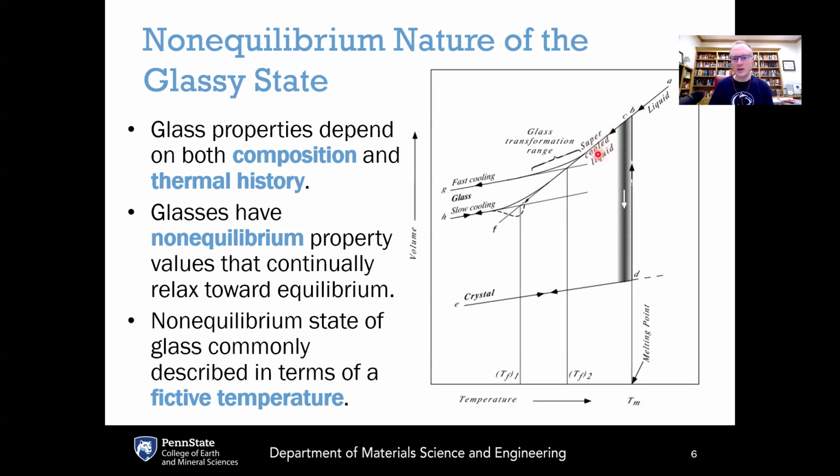The supercooled liquid is not the thermodynamic equilibrium. It is what is called a metastable equilibrium, meaning that there is a lower free energy phase available, which is the crystal phase, but it takes a phase transition in order to get that. So the supercooled liquid, if you just leave it alone, would be stable, but in the limit of very long time and when it's exposed to various thermal perturbations, over time it will undergo a phase change and crystallize.